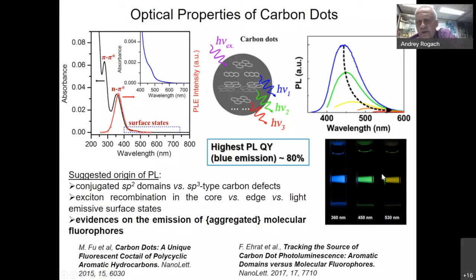But actually these photographs were taken from one and the same sample. These are three different cuvettes, but inside is one and the same sample. We just excited them at different excitation wavelengths. If we excite them at UV wavelengths, they will emit blue light. If we excite them at longer wavelengths, 450, they will emit green light. If we excite them at 530 nanometers, they will emit orange light.